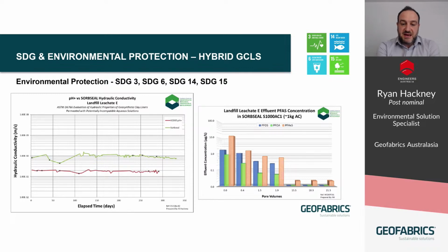Again, we can modify a geosynthetic clay liner by incorporating other additives. This can include polymers, ion exchange resins, and powders such as activated carbon. One such example here is the incorporation of activated carbon and polymers into the geosynthetic clay liner, and this gives the GCL an additional function. As well as functioning as a low permeability barrier, the addition of activated carbon, for example, can absorb contaminants such as per- and polyfluoroalkyl substances, but it can also entrap free cyanides as well. Activated carbon is known to absorb free cyanide. So again, by incorporating other additives into a geosynthetic clay liner with the bentonite, we can achieve additional functions through that process.